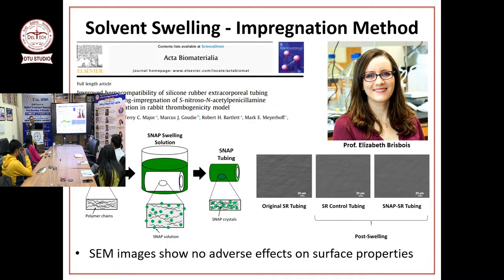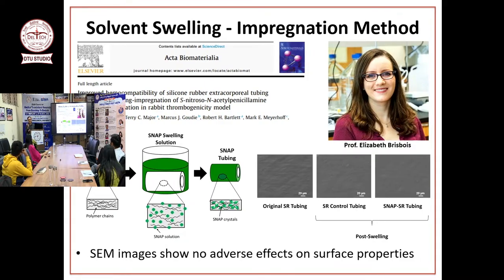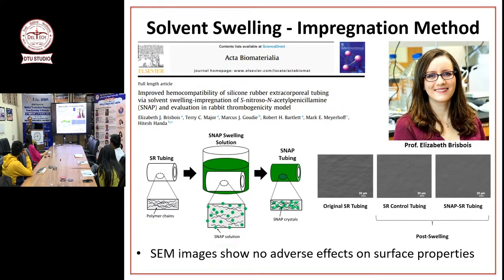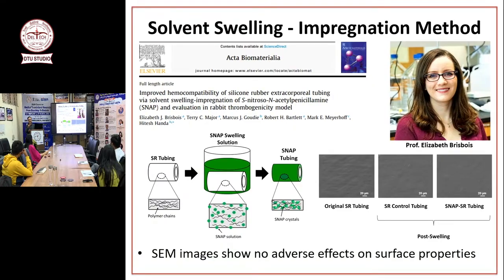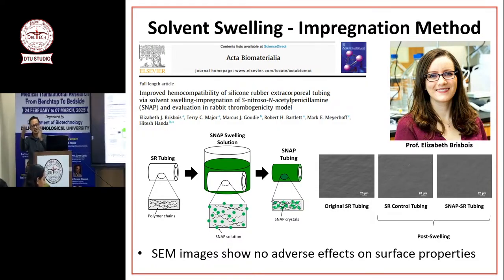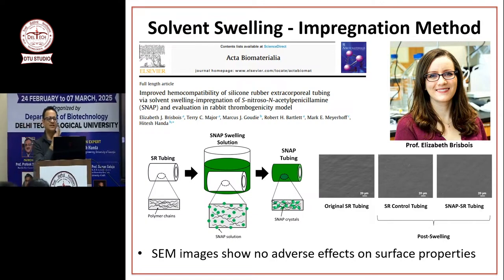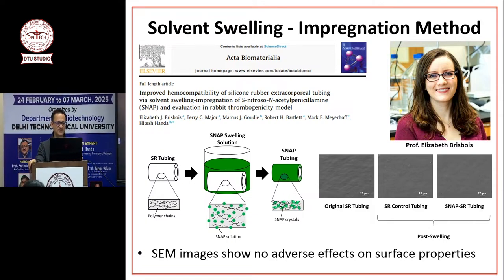Yes, but we also showed if you add 15 weight% SNAP or 20 weight% SNAP, it will happen, but less of it. But your material becomes less strong and it starts becoming a little bit brittle. You are compromising on the strength of the material by adding too much NO donor. Otherwise, you can always say, hey, let's add 50% SNAP. That's great, we can have more NO release, but the strength of your material will go down tremendously.